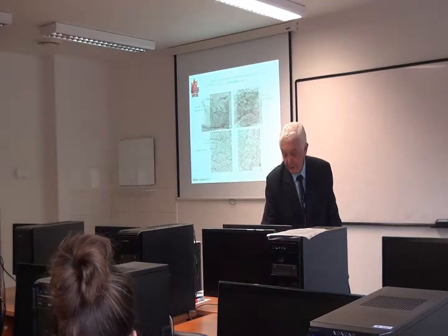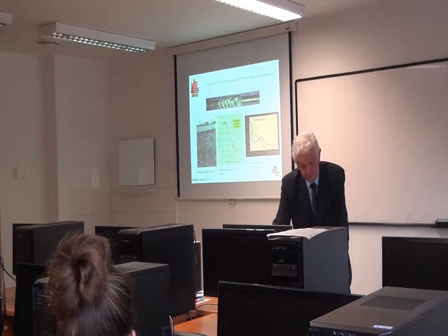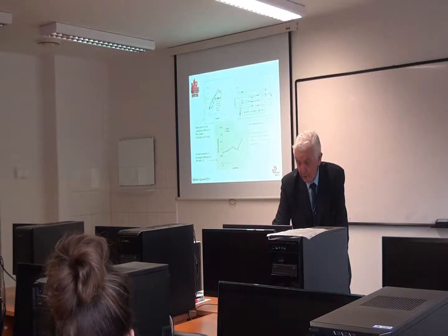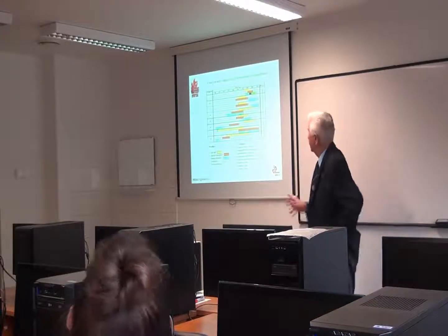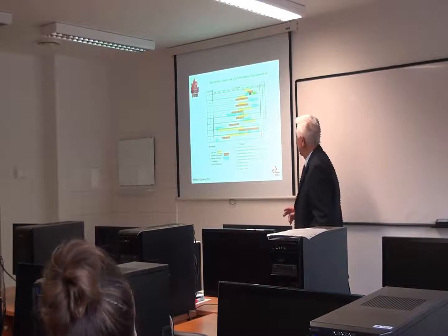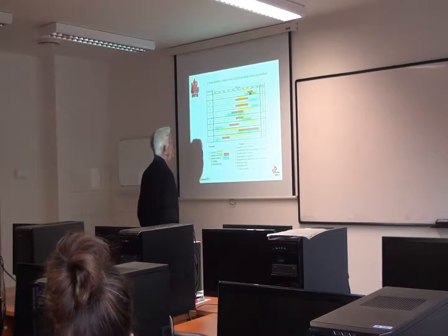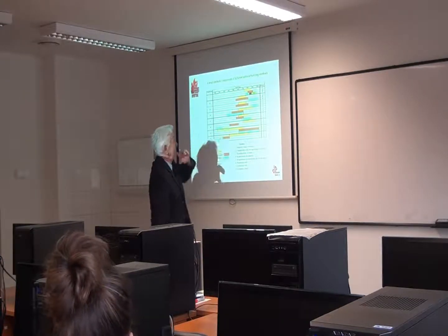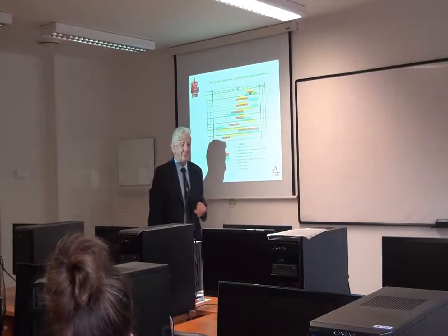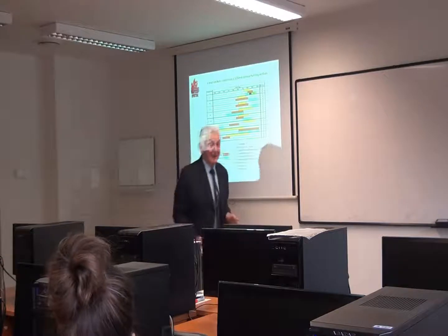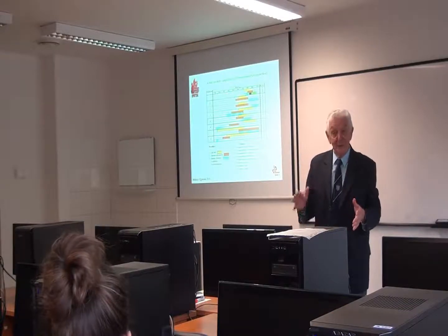But these are important. Certainly, we can talk a lot about this, and also about different possibilities for testing the wear resistance, which you learned. But this could still be interesting, a synthetic comparison of different nitrocarburizing methods. You see salt bath, gaseous atmosphere, and plasma. What is important? Unfortunately, we can say that the salt bath gives the best results. But as we have a lot of environmental regulations, unfortunately the salt bath is slowly being excluded.